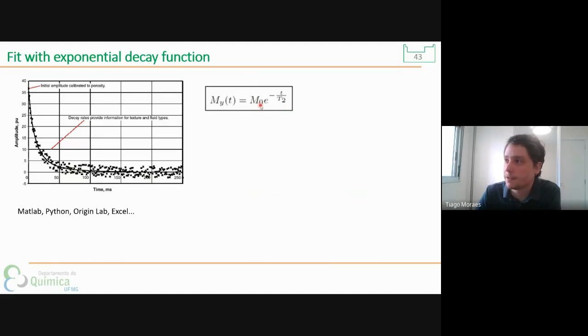So here M0 is just the value of the initial amplitude of the signal. Then you see that you have an exponential with a minus here, that is a decay. The t is the time scale here, and T2 is the constant that describes the velocity of this decay, right? So with this equation, we can fit the signal using different software like MATLAB, Python, Origin Lab, Excel, and determine this value to do our analysis.